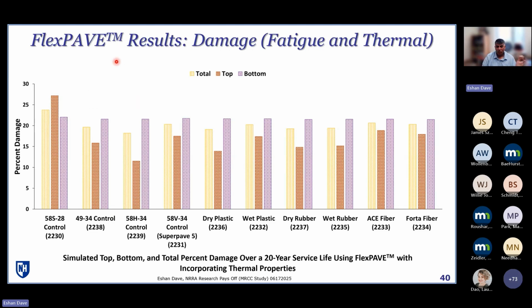It's actually a trademark of USDOT and the Federal Highway Administration. It's more looking at cyclic degradation, so it's not designed for reflective cracking. It's more for damage from repetitive traffic and thermal cycling. And there also the results align a little bit better with your lab test results, where control showed again a very high damage potential compared to other mixtures.